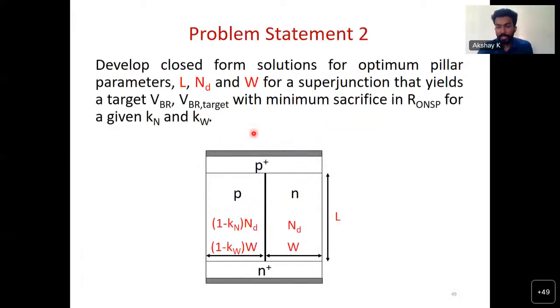And the second problem statement, previously we saw an ideal junction. Now we had also solved for superjunction by taking into account process variation, which means that we had initially assumed the doping and width are exactly equal for the N and P pillars. We had also shown calculations where we allow an imbalance between the doping and width of the N and P pillars. And the imbalance factors called Kn and Kw are decided by the process variation, which means that ideally you want the N and P pillar to have the exact same doping and width. But when you manufacture, you won't be able to exactly realize the doping and width that you target. There will always be slight deviations from what you target. And that deviation is taken care of by this Kn and Kw. It could be, let's say, 0.1 or 0.2, which means a 10% deviation in the N pillar or 20% deviation in the N pillar and so on.